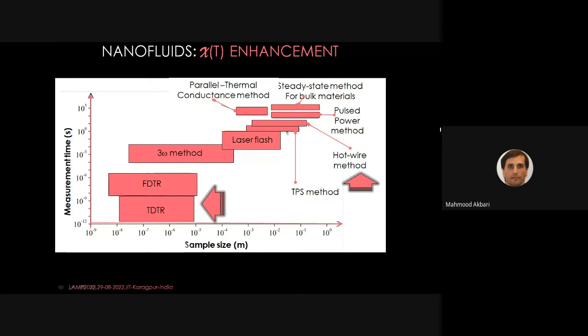Colleagues, you would agree with me that in effect the hot wire approach is not effective. The ones which are very effective are laser based. The transient thermoreflectance methods are far better than the hot wire and the classical ones where the sample size must be bulky. Laser-based optical methods are far better. Why? Because they require a minute amount of material, and the measurement time can be in milliseconds and microseconds, even faster.